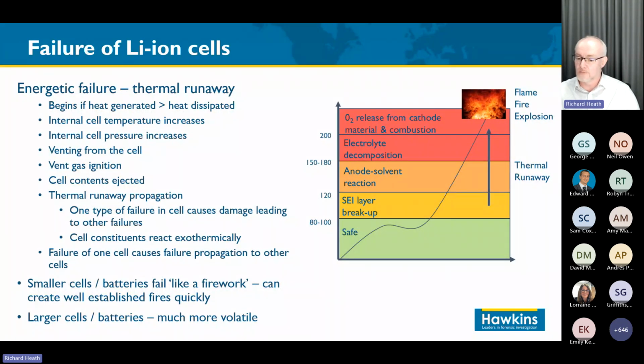So you can get a much more well-established fire much more rapidly than with a more conventional accidental cause of fire, electrical fault in an appliance. And of course, with larger cells and batteries like those we're seeing in e-bikes and e-scooters, you get an even more volatile reaction. So when fire brigades are turning up to fires started by lithium-ion batteries, they're finding they're far more well-established already.